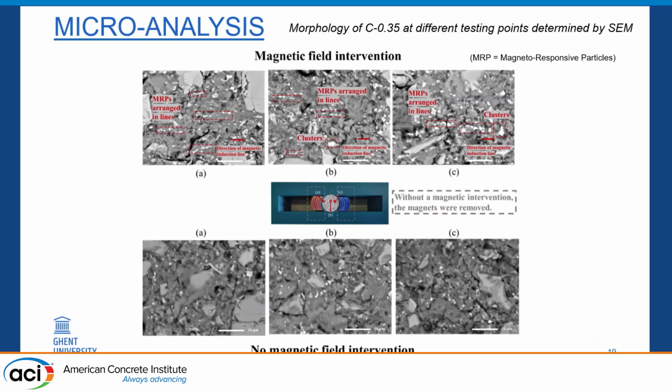We did some electron microscopy where we saw indeed that we had some chain formation in the case where the magnetic field was applied, contrary to the standard reference case. Now I have better results. My student showed me last week some images obtained with computed microtomography, and we even have three-dimensional images that we can rotate, and there you clearly see the chain formation of the particles.